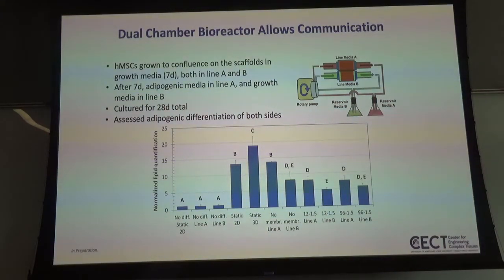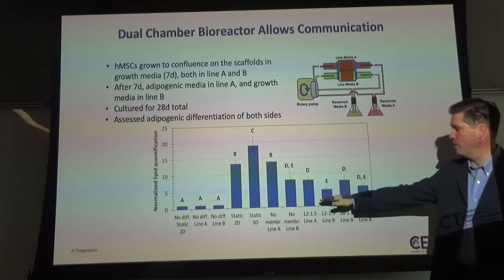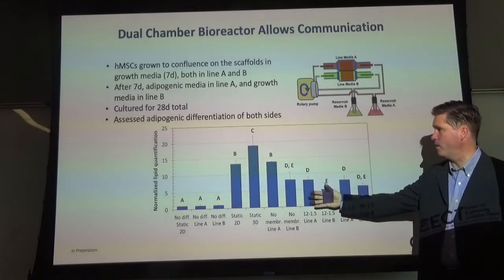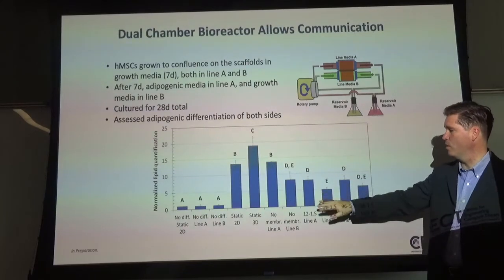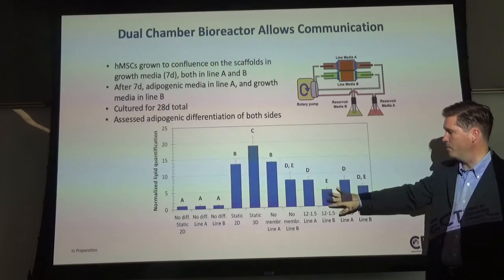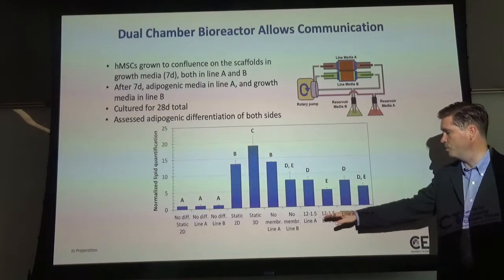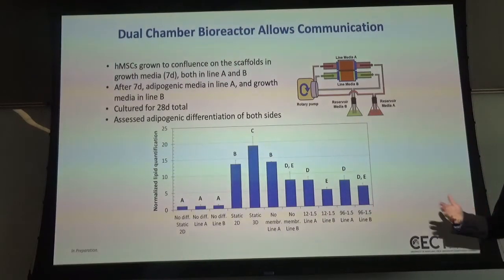And cultured these for 28 days and was able to demonstrate that he did indeed find, again using lipid as a marker, lipid expression in both the top and the bottom chambers for multiple membrane types, and correlating the expression to the membrane cross-linking, or ultimately the membrane porosity.